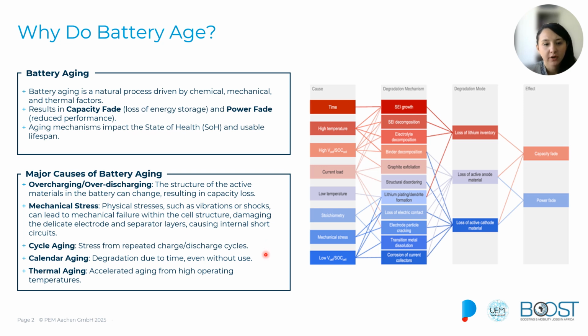Another major factor for aging is going to be cycling aging. Each time that the battery goes through a charge and a discharge cycle, a small amount of the battery will wear out, and this wear occurs naturally. The more cycles that the battery undergoes, the more degradation it accumulates, and eventually it will reduce little by little the total capacity. Even when a battery isn't in use, it will also experience another type of degradation, that is the calendar aging. This type of degradation happens due to the slow and ongoing chemical reactions within the battery over time, and this happens even if the battery is sitting on a shelf and is not being used. And finally, one of the most relevant ones is the thermal aging.